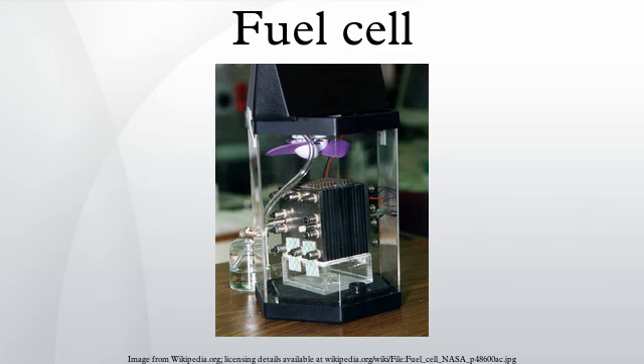One such challenge is the potential for carbon dust to build up on the anode, which slows down the internal reforming process. Research to address this carbon coking issue at the University of Pennsylvania has shown that the use of copper-based cermet can reduce coking and the loss of performance. Another disadvantage of SOFC systems is slow startup time, making SOFCs less useful for mobile applications.